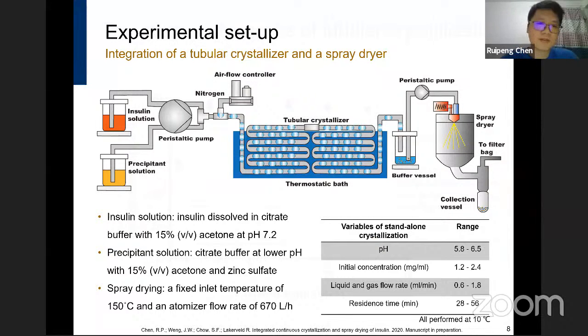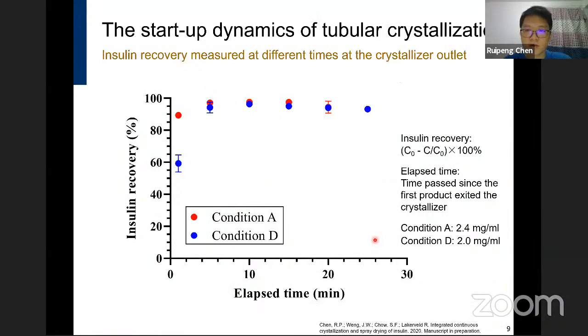So we can first look at the startup dynamics of the tubular crystallization. This is monitored by characterizing the insulin recovery and the CSD at the crystallizer outlet at different times. Here, the insulin recovery is defined like this, in which C0 is the initial concentration and C is the measured concentration at the crystallizer outlet. The elapsed time is the time passed since the first product exited the crystallizer, and two conditions were selected, which differ only in the initial concentration. Triplicate experiments were done for each condition. As we can see in this figure, both conditions have a relatively low recovery at the very beginning, but soon, in around 5 minutes, both conditions reach a plateau and remain approximately constant for the remaining operating time.